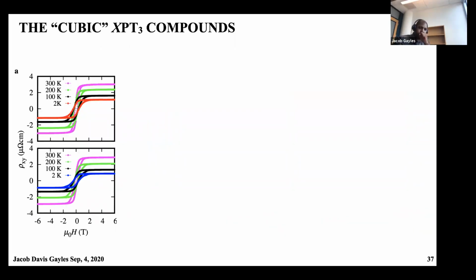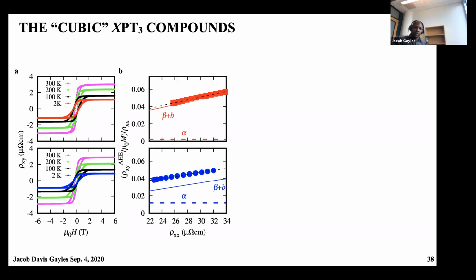Further on, we measured the anomalous Hall effect of these materials in the experiments. So this is here just the anomalous Hall effect as a function of the field, which shows the same hysteresis that you had for the out-of-plane material at different temperatures. And what we can do is separate the side jump plus intrinsic from the skew scattering. And for the two different samples, we actually get quite different skew scatterings, which suggests that one of the samples has more impurities and the growth is a bit different here.